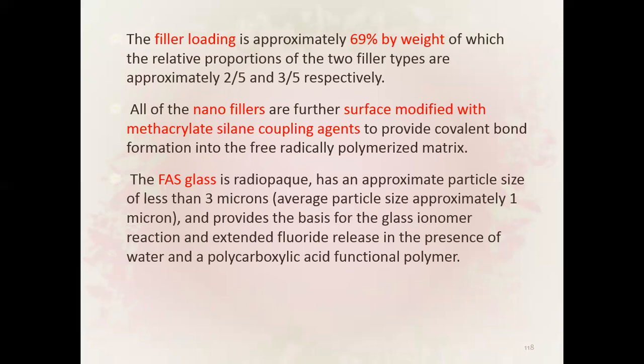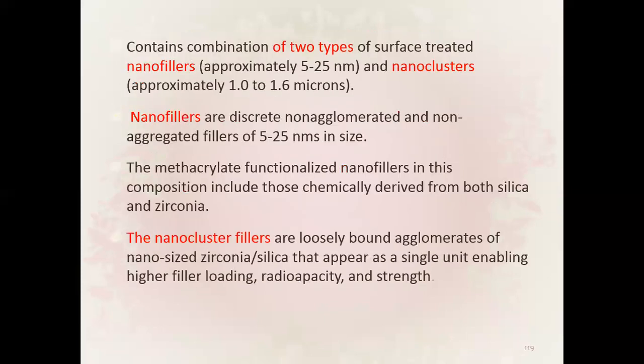The FAS glass is radio-opaque with an approximate particle size of less than 3 microns and provides the basis for the glass ionomer reaction — extended fluoride release in the presence of water and polycarboxylic acid functional polymer. It contains two types of surface treated nano fillers: nano fillers and nano clusters.